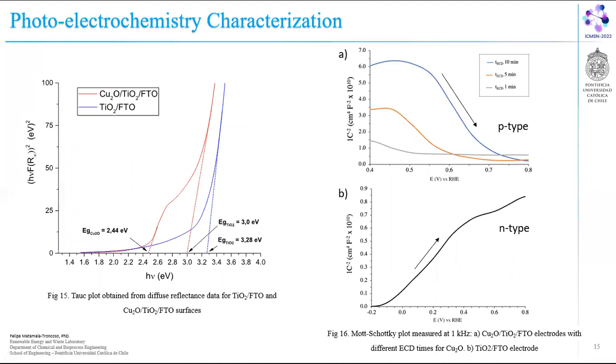On the other hand, diffuse reflectance analysis was performed, obtaining the Tauc plot, where it's possible to analyze the interaction between both semiconductors. In this, observe that the titanium dioxide band gap is similar to the theoretical values reported in the blue line, and in the red line, the presence of the cuprite modifies it, showing a negative shift of this band toward the red spectrum, given the electronic rearrangement generated by the interaction with the cuprite.